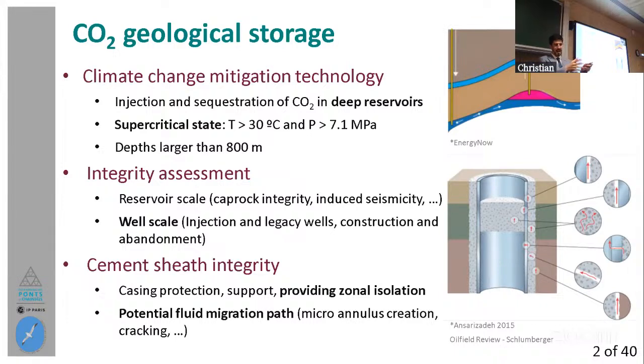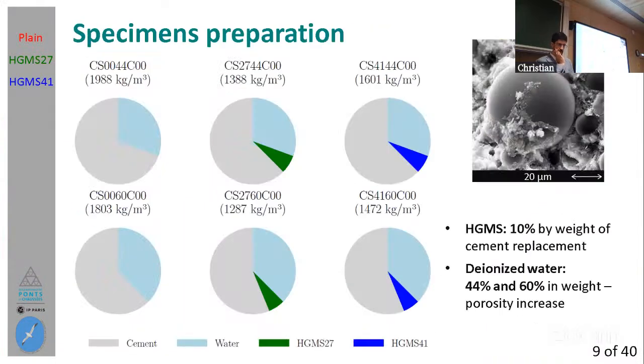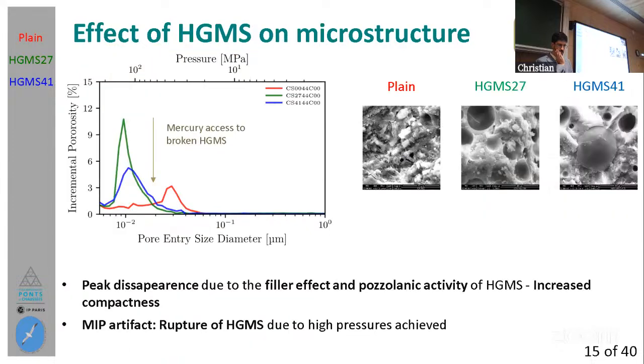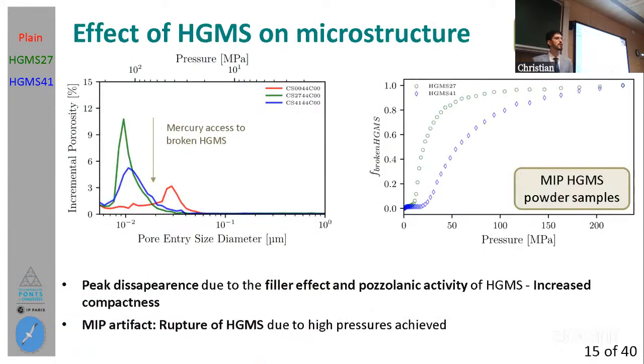So, as far as I have now, from the results that I obtained, and I will show you them here, give me 1 minute. There. As for the result that I obtained here, I was able to see that the spheres 27 were already starting to break. This pressure corresponds to, if I remember well, around 15 megapascals. Accounting also for the pozzolanic activity, I would recommend, if I don't have the actual number, to apply them to pressures even lower than 10 megapascals, to have some idea that they will reduce the thickness at some point.